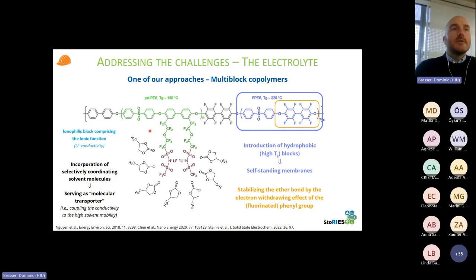And then to overcome the issue of the limited conductivity mentioned on the previous slide for PEO, basically, we incorporate small molecules that are also frequently used in liquid electrolytes, such as here propylene carbonate. And the idea is that these molecules need to have a high dielectric constant, right? Because then they can selectively coordinate the lithium cations. And by this, basically, serving as, we call them molecular transporter. So serving as a kind of transporter to help the lithium cation to jump from one anionic site to another by several effects, right? Reducing somehow the activation energy that is needed by coordinating the lithium cation basically, and then helping to jump.